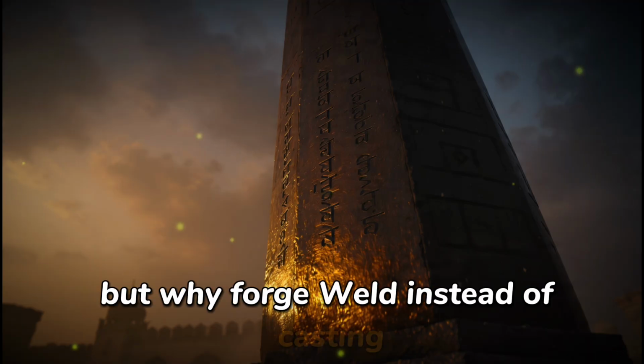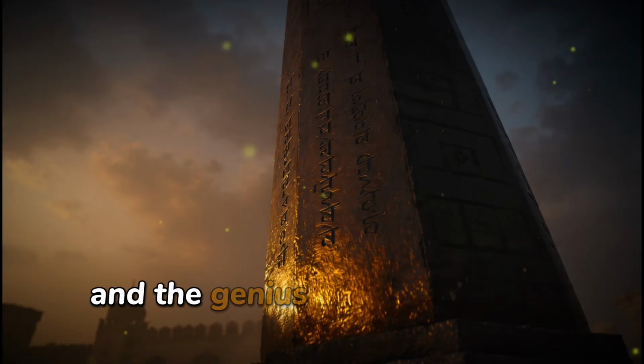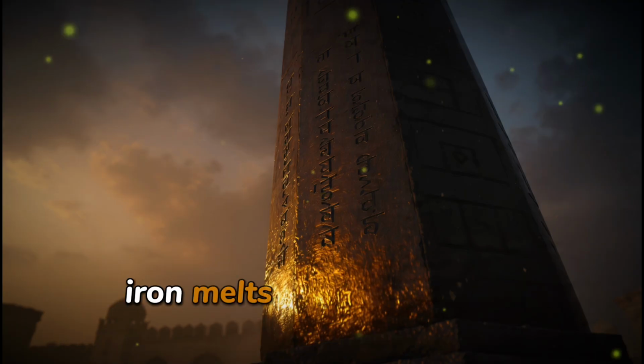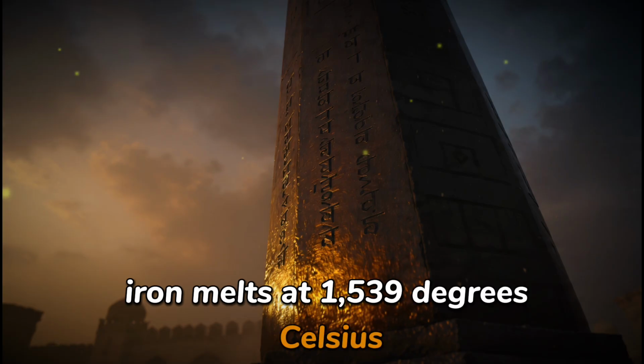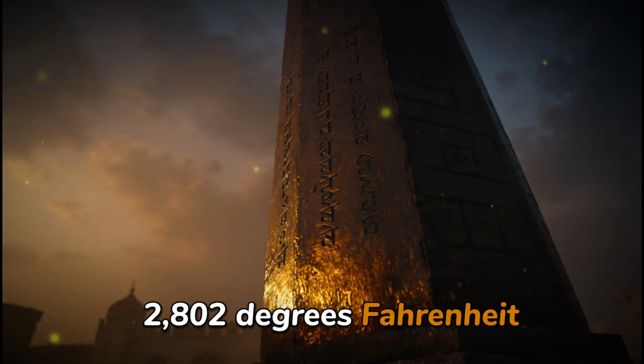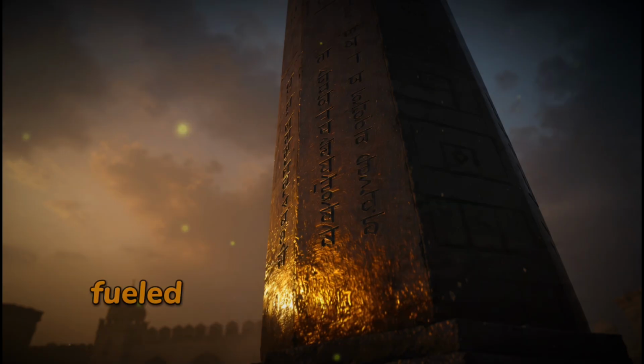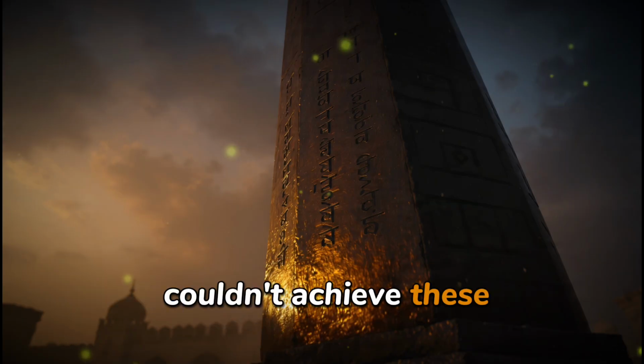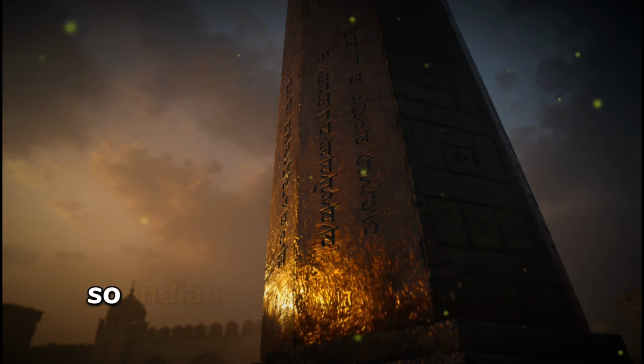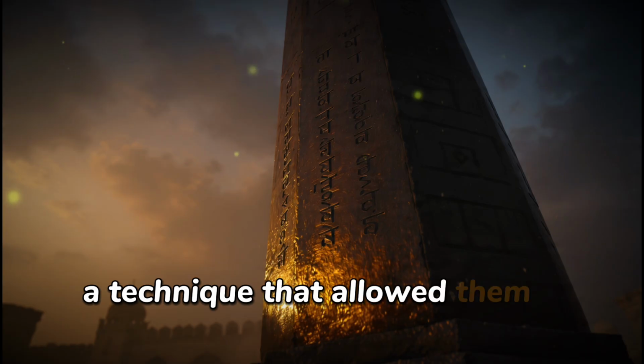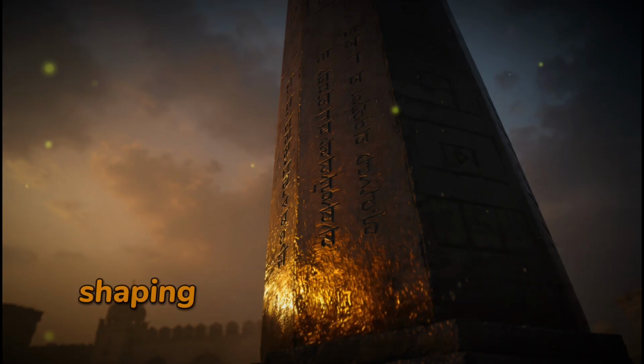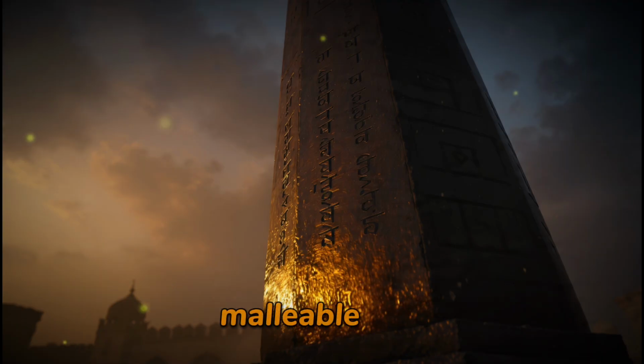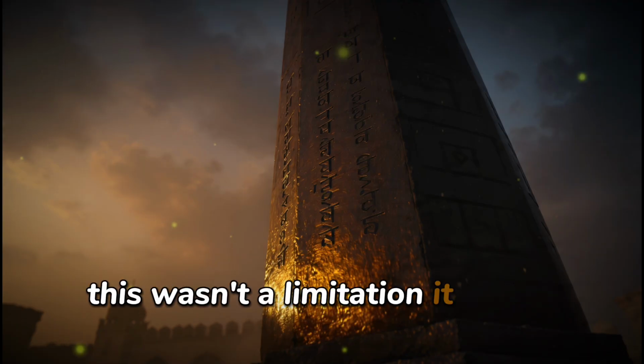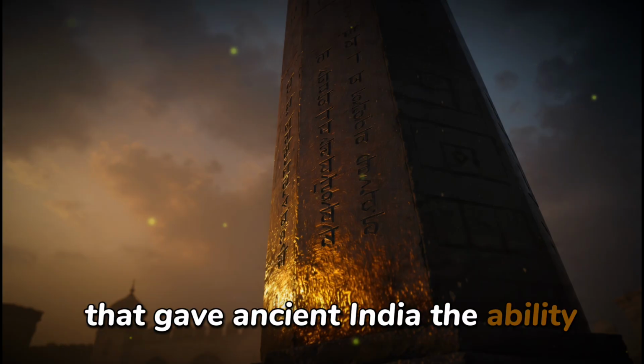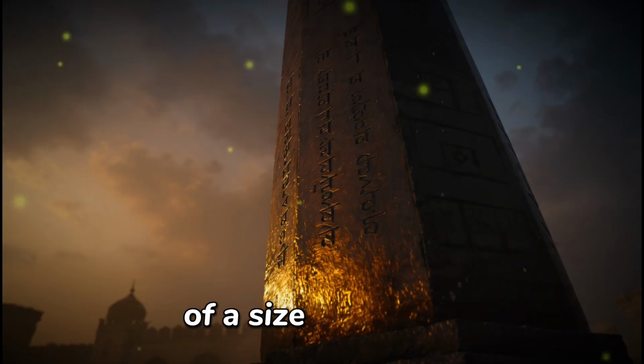But why forge weld instead of casting? The answer reveals the limitations and the genius of ancient Indian metallurgy. Iron melts at 1,539 degrees Celsius, 2,802 degrees Fahrenheit. Ancient Indian furnaces, fueled by charcoal and powered by bellows, couldn't achieve these temperatures. Casting was impossible. So Indian blacksmiths developed forge welding, a technique that allowed them to work with iron below its melting point, shaping and joining pieces in their red-hot, malleable state. This wasn't a limitation. It was an innovation that gave ancient India the ability to create wrought iron structures of a size and quality that European smiths wouldn't match for more than 1,000 years.